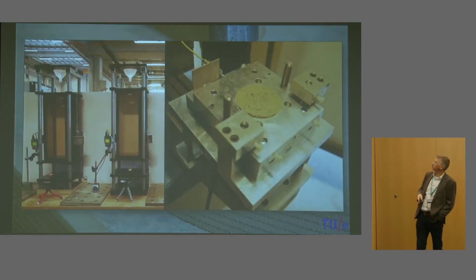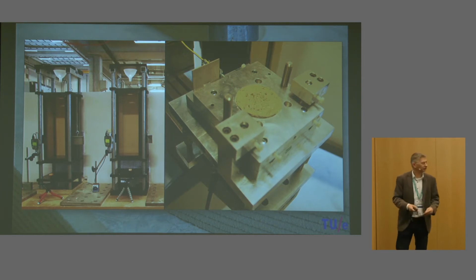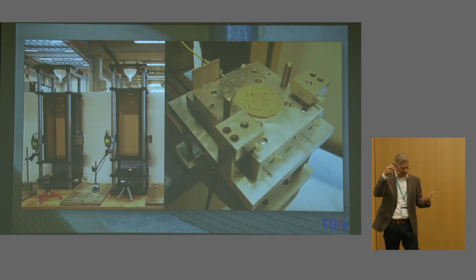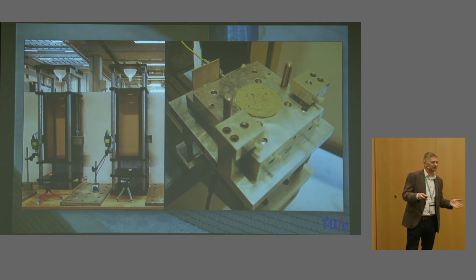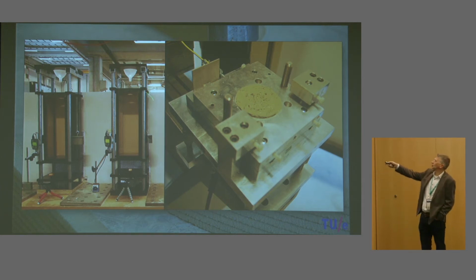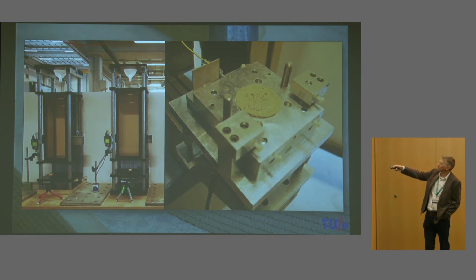So now the research part came in. We need to study not only the properties of hardened concrete, as we do on cubes and cylinders with compression tests, but we also had to figure out the properties of our fresh concrete. How to do that? We just considered it being mud, soil. So we did compression tests on the soil, sand in here, sample underneath, a kind of a measuring device here, a load cell to measure the force coming from the sand, and a displacement. This is in compression, this is in shear.